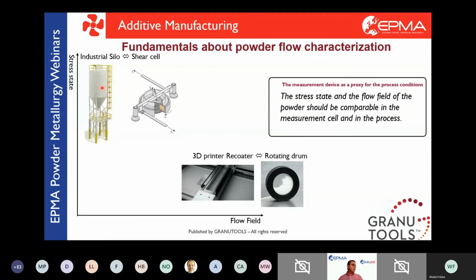If I want to understand the powder behavior inside an industrial silo, I need to characterize the cohesive forces. But in the silo, we have very high stress states and very low flow fields. This means the powder is under a huge amount of stress and it's barely moving. So you need to find an instrument that will reproduce those process conditions, like a shear cell, for example, where you need to put pressure on the powder and to move very, very slowly.